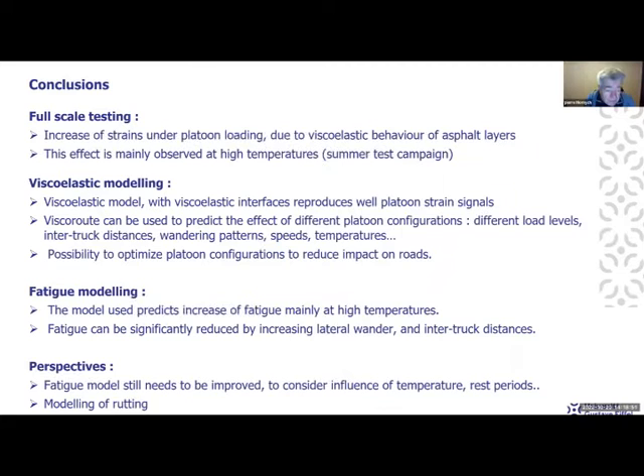And then with the multi-peak fatigue model, we were able to predict the fatigue under platoon loading, and we found that there is an increase of fatigue mainly at high temperatures, and that fatigue can be reduced by increasing lateral wander and also inter-truck distances.